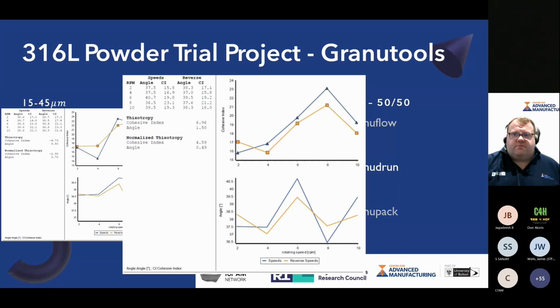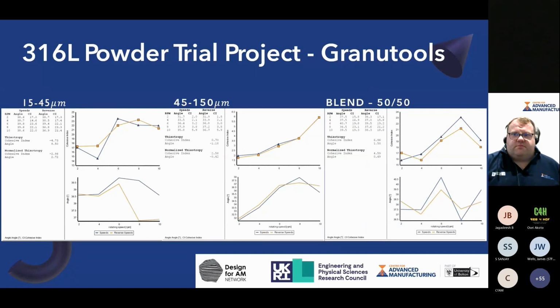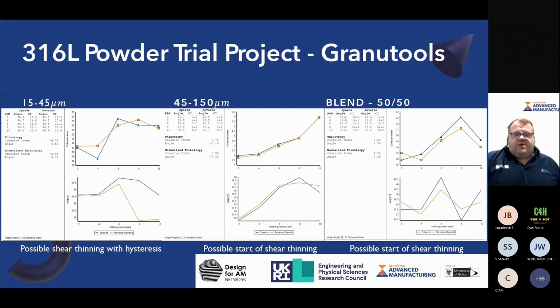What does that mean? It means that larger powder is having an effect on flowability, but it also means that the blend is potentially starting to become less cohesive and therefore easier flowing at higher speeds. Again, there's an additional test to be done here, maybe looking at up to 20 RPM. So in all cases, there certainly seems to be a potential start of some shear thinning. We can see that from the way that the graphs are all starting to turn down, and in this case, this is slightly distorted.